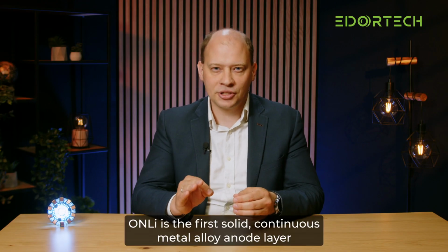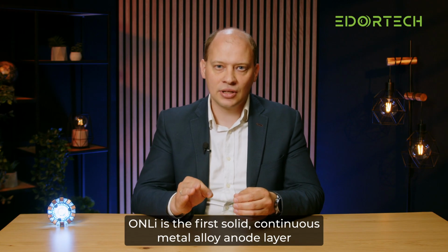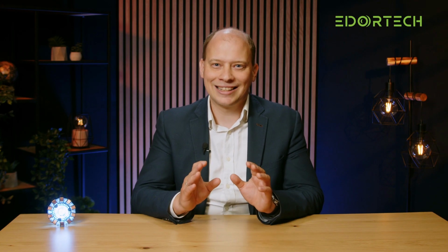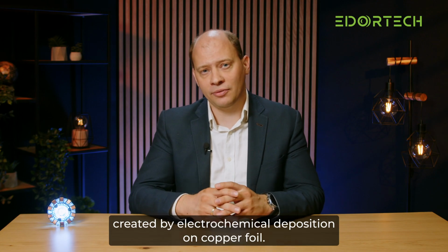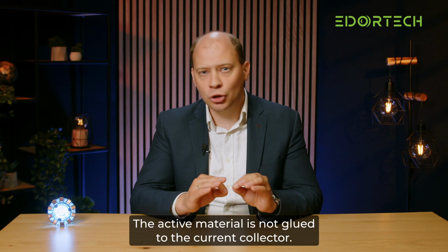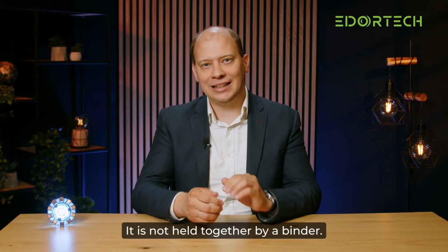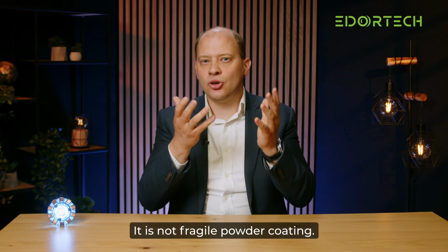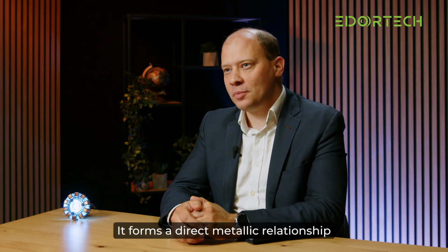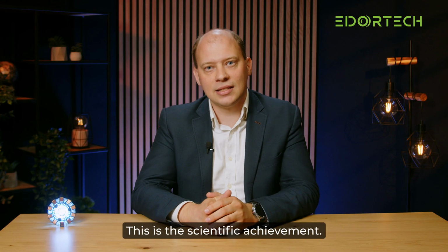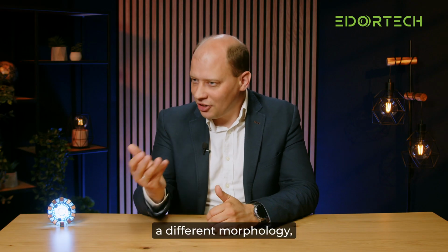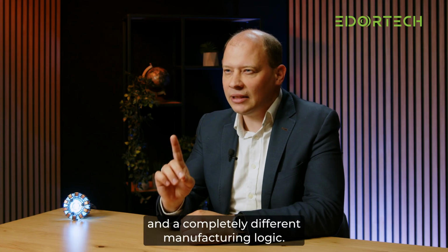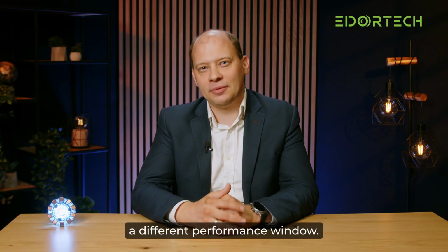ONLi is the first solid, continuous metal alloy anode layer created by electrochemical deposition on copper foil. The active material is not glued to the current collector. It is not held together by a binder. It is not a fragile powder coating. It forms a direct metallic relationship with the copper substrate. This is the scientific achievement. A different material, a different morphology, and a completely different manufacturing logic. And because of that, a different performance window.